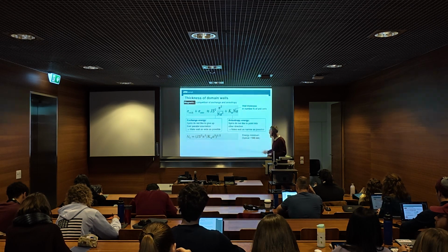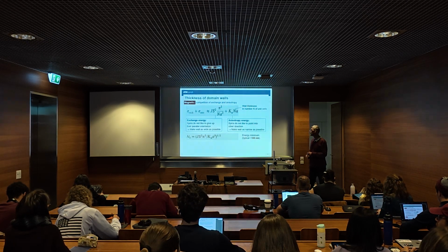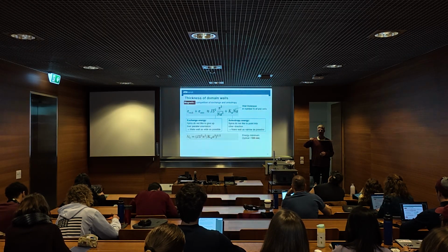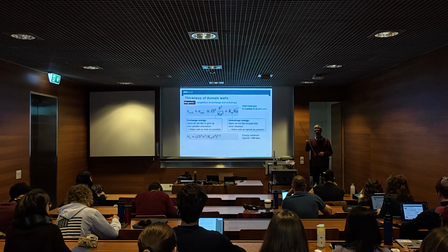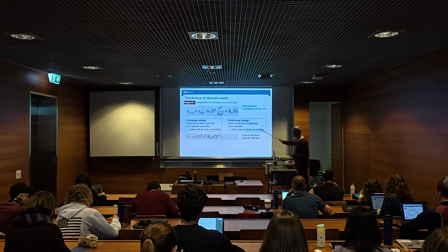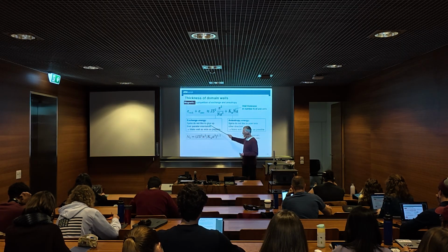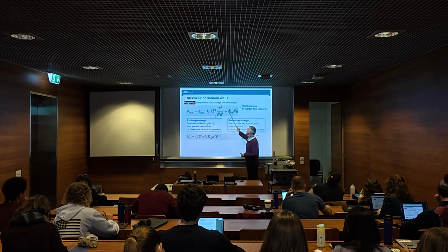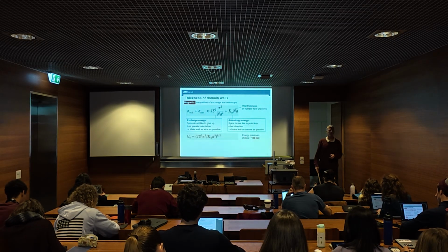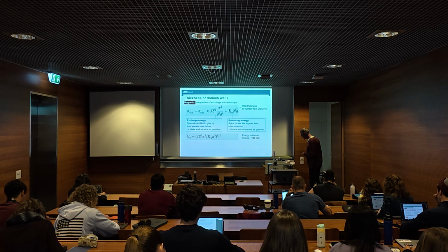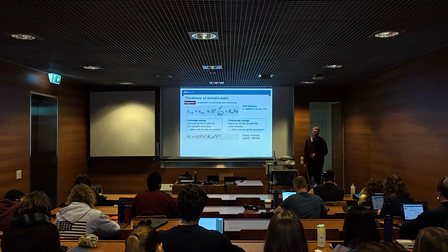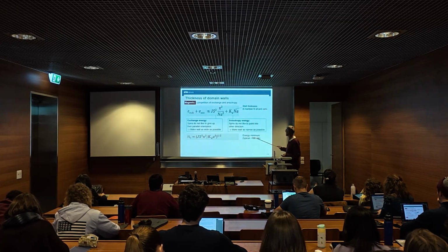On the other hand, anisotropy energy doesn't want spins to point into other directions. So that would favor very narrow domain walls, because it hates this. It would not tolerate a lot of this. It would just say, okay, one domain, then immediately boom. Anisotropy wants narrow domain walls, exchange wants wide domain walls. You add them up, you minimize, and then you get a certain wall width as a compromise. For ferromagnetic domain walls, it's typically like 10 to 100 nanometers, very rough.